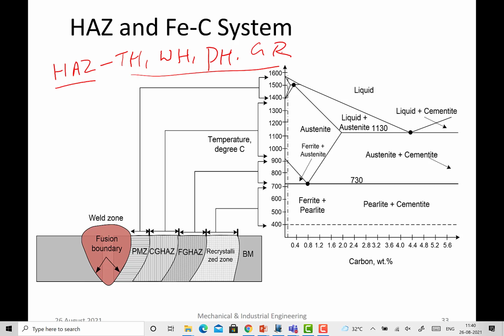If a metal has been strengthened by a combination of all these, then you will notice that there is a combined change from the heat applied, or increase in temperature, which is taking place in the heat affected zone. So just for your understanding, here for plain carbon steel up to 730 there is no change in the phase, except that there is recrystallization. So this temperature band from say 400 to 730 is where new grains will be formed. So you can say that is the recrystallization temperature zone.